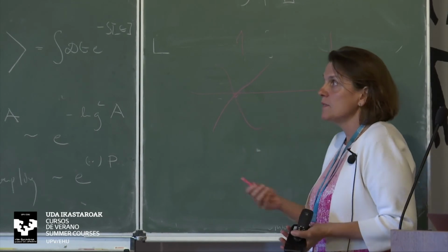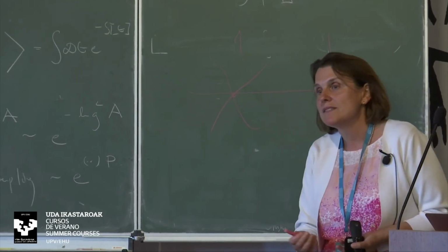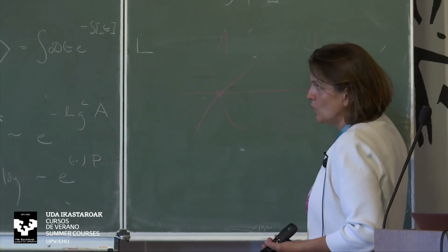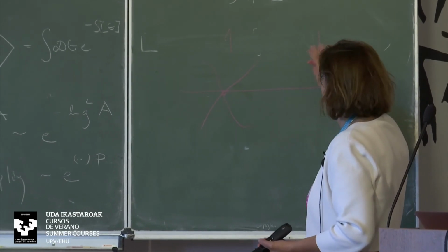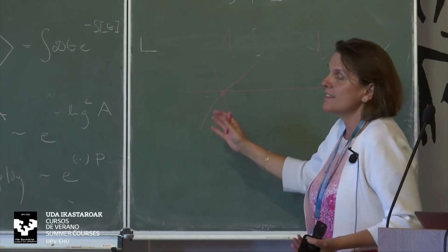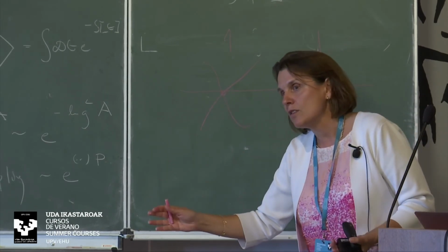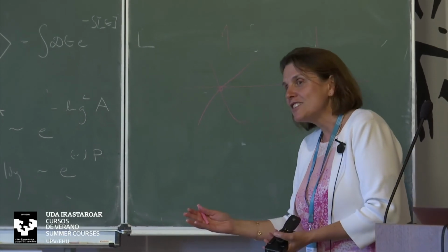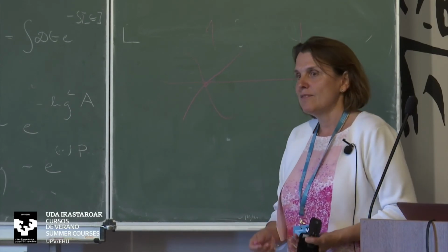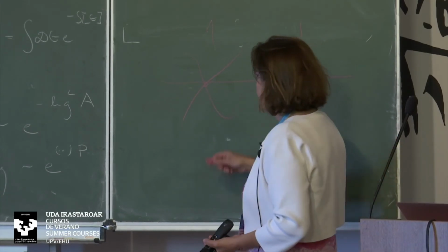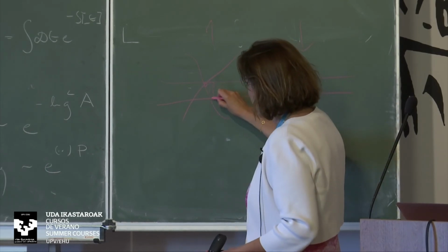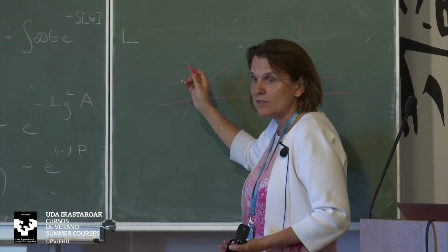The families which have half metallic ferromagnets, which have a gap in one spin direction and some crossing bands, I think there's a high probability that you find a crossing around the Fermi energy, and if you can dope them, then you have even nice Weyl points. In cobalt titanium tin, unfortunately it's here, so you really have to put a lot of electrons in.